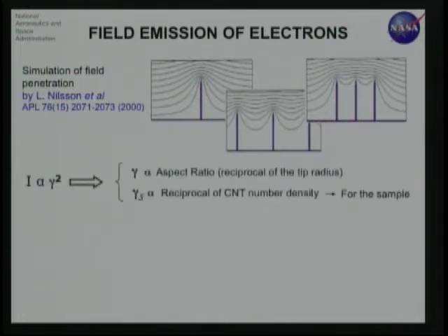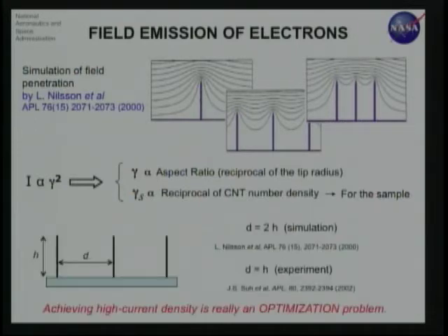Gamma is a function that varies as the aspect ratio, and it's reciprocal to the CNT number density, which basically relates to your electrostatic screening effect. There is multiple work that has been done by different groups, and a group led by Nilsson said it's really an optimization problem: how do you bring so many emitters together so that you have a good combination of number density as well as low electrostatic screening?